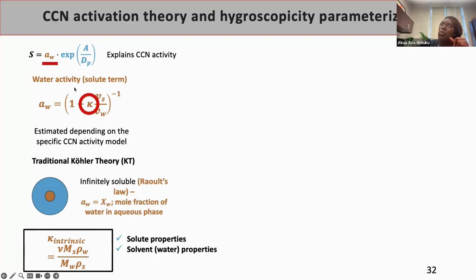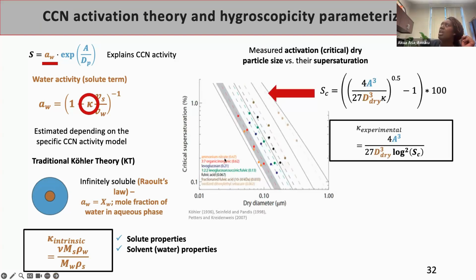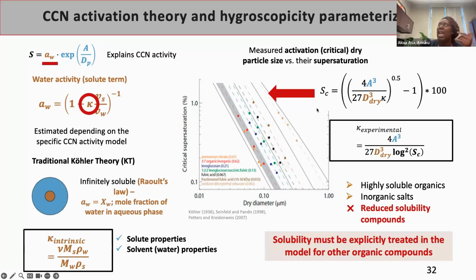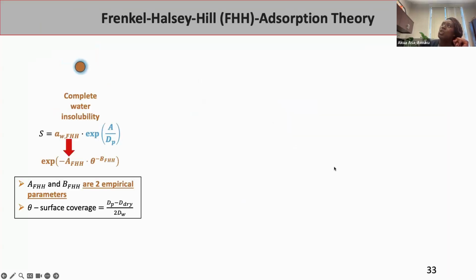And so what we know through Köhler theory is that the intrinsic Köhler theory, which is what I plotted in the original graphs where kappa was 0.002, is really a function of its molecular weight and its density of that solute property, in addition to its van 't Hoff factor, which for most organics is 1. And when the molecular weight is really, really huge, the kappa really should go down. And we see this within our data sets, and we see that for inorganic, highly soluble salts, kappa works well. But when you have solubilities that are very low or effectively water insoluble, this kappa Köhler theory should not be applied. And there are several studies that go through this. All right, so what could be applied?